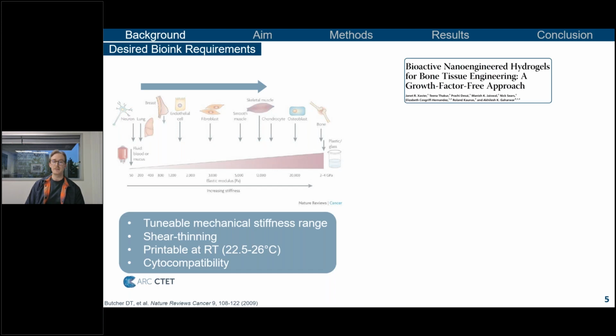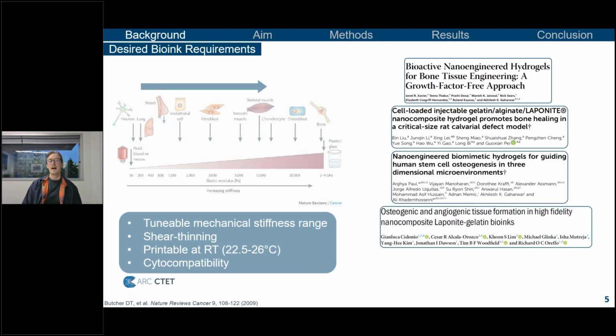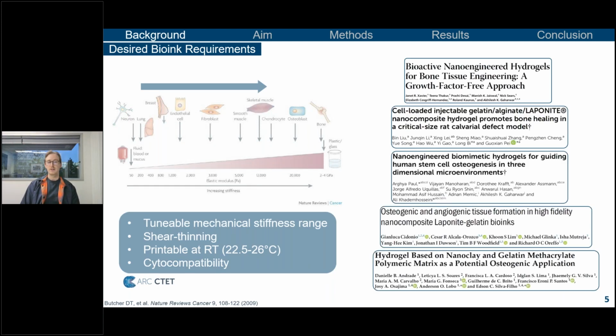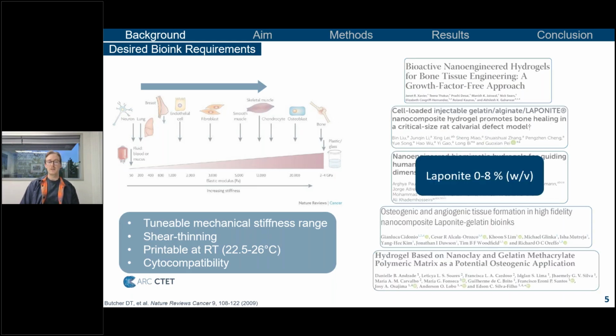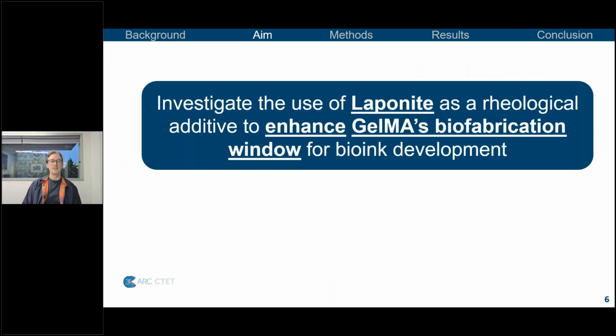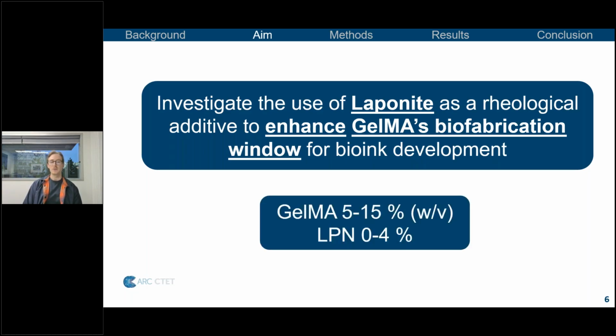Laponite has been extensively used in prior papers and studies for a number of different applications, from osteogenesis to vasculogenesis, looking at large bone defects. Many people currently use laponite at a concentration of 0 to 8%. This led us to our aim: to investigate the use of laponite as a rheological additive to see if it would enhance GelMA biofabrication, looking at a GelMA concentration ranging from 5 to 15% to account for the mechanical stiffness range we'd like to achieve, and at the lower concentration end of laponite, 0 to 4%.